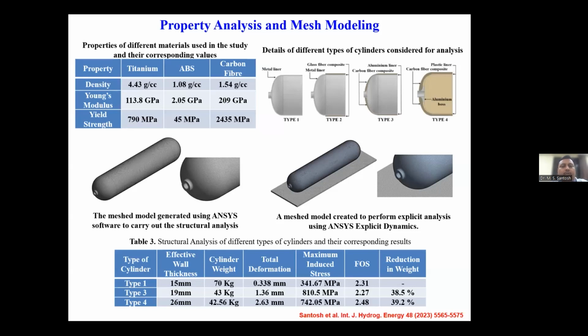ABS was not capable enough to hold high pressures of hydrogen. So in order to make it suitable, we blended 10% of carbon fiber into the ABS matrix and then tested the efficiency. When we carried out some of the preliminary property analysis, such as density, Young's modulus, and yield strength, we were able to identify that ABS improved its properties gradually with the addition of carbon fiber, whereas titanium, being a metal, had its own strengths and weaknesses as well. But carbon fiber individually is much more capable and multifold stronger and offers a better performance compared to ABS.